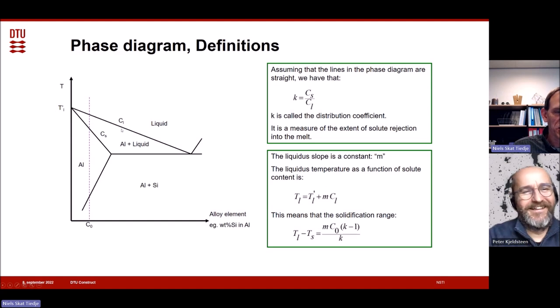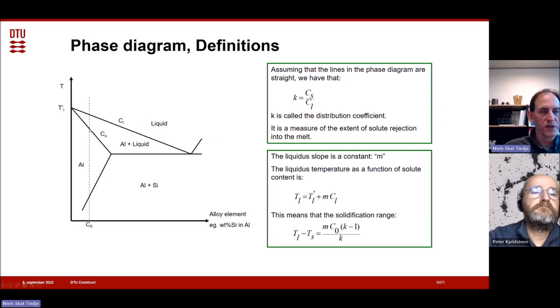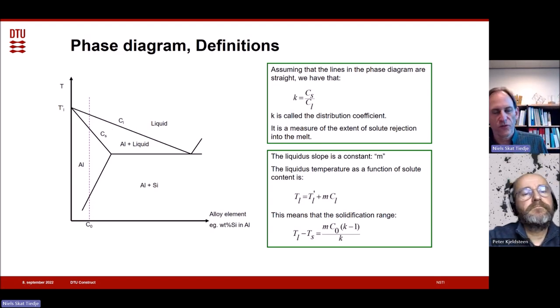If we look at a section of a eutectic phase diagram, if we have an alloy with this composition C naught, we know that it will begin to solidify at the liquidus temperature, and solidification theoretically should be over and done with when we reach this point, which is the solidus temperature. But we also know if we're somewhere in between, in this triangle, you will have two phases. You will have a solid phase with low alloy content and a liquid phase with a high alloy content. So it's basically separating. It's sort of liquid and solid becoming like oil and water, more or less.